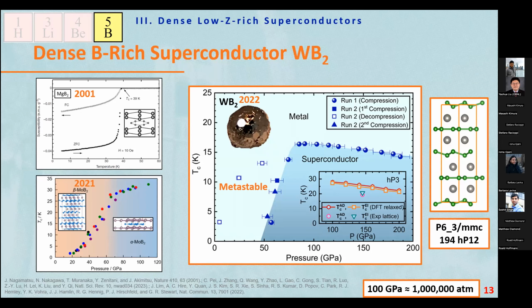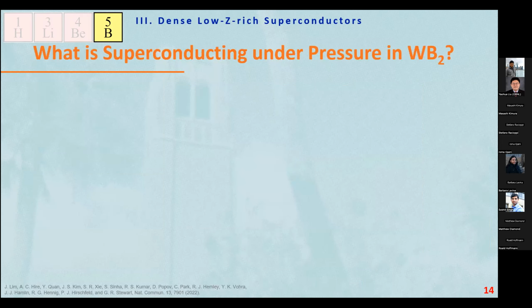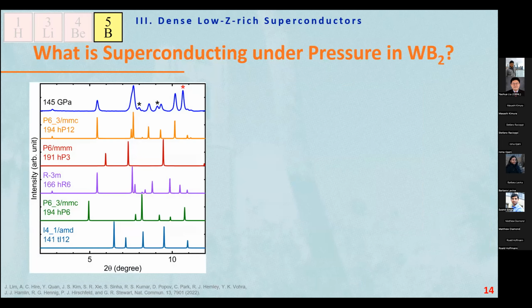the next step is doing the X-ray diffraction measurement under pressure. Thanks to the CDAC support, we did the X-ray diffraction right away, quickly, and then we found that there's no structural transition. The initial structure, the buckled layer structure, remains up to 145 GPa. So we don't have any MgB2-like structure.